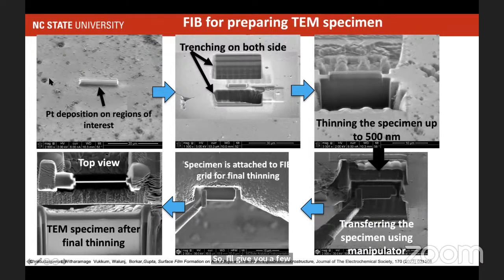What we do is very simple experiments. We take our material, we put it in a corrosive environment or do a certain corrosion test. Say, for example, sometimes we want to study the passive film and we want to exclusively grow the passive film, where the maximum thickness would be like 10 nanometers or something. So we have those passive films on the metals either after electrochemical tests or after simple immersion tests, right? We take them to a FIB, a focused ion beam. We deposit a platinum layer on top to protect the material, since we're going to make a TEM specimen out of it. We make a trench around it on both sides, and then we make this thin specimen, lift it out, and take that very thin sample to the TEM, right?